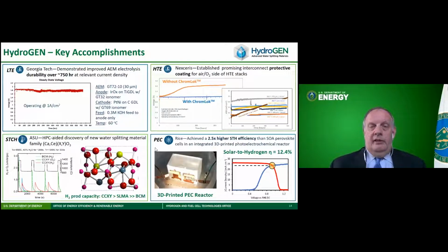And then photoelectrochemical, again, trying to get the cost down with a stable material. People have been looking at perovskites, and work at Rice University has just recently demonstrated a 2.5 times increase in the sun to hydrogen efficiency over the best state-of-the-art perovskite material. And this is integrated in a low-cost 3D printed photoelectrochemical reactor cell. So a big improvement in the efficiency for this perovskite material.